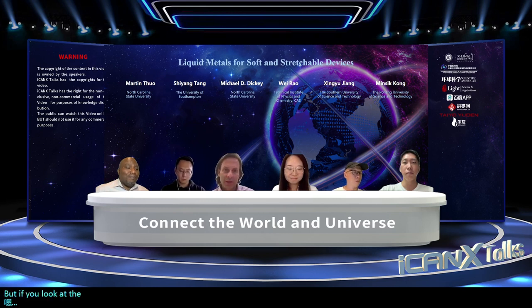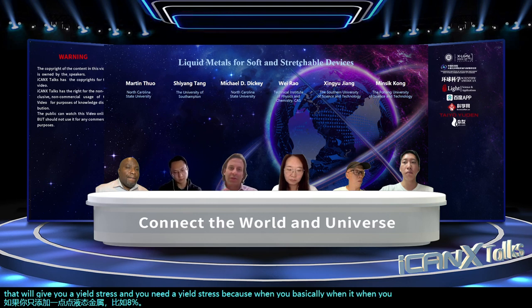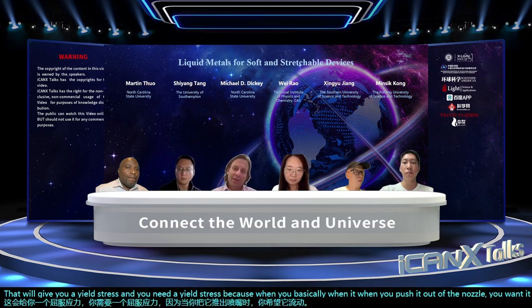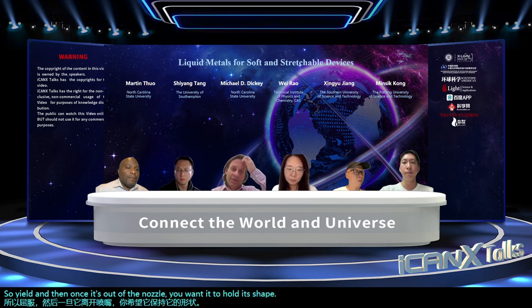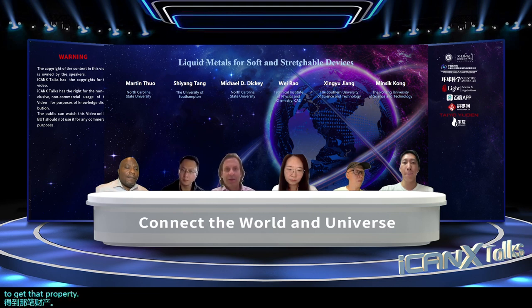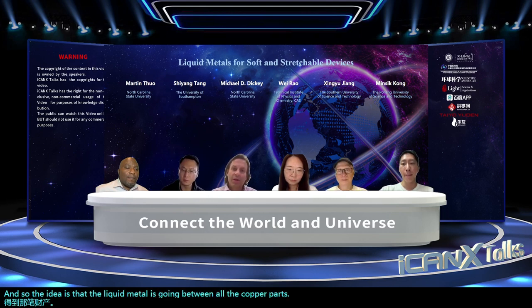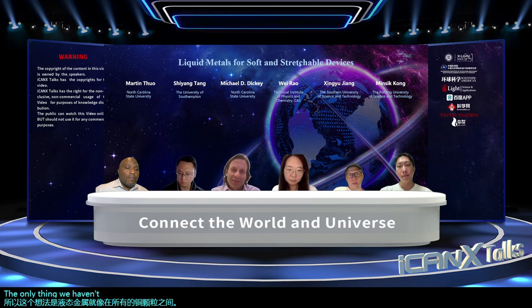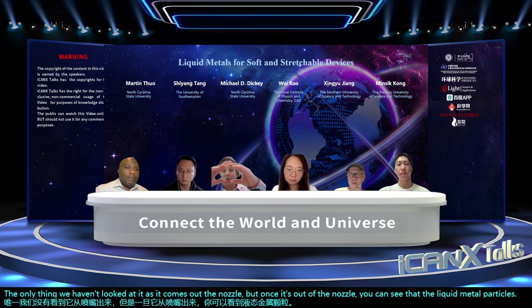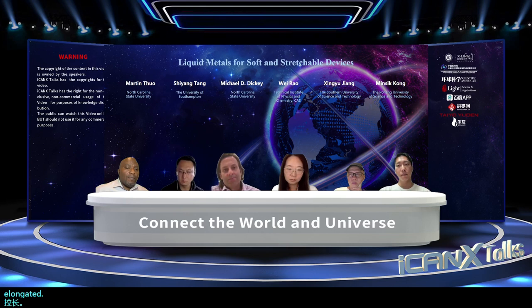But if you look at the rheology, what's interesting is that if you only add a little bit of liquid metal, like 8%, that will give you a yield stress. And you need a yield stress because when you push it out of the nozzle, you want it to flow, so yield. And then once it's out of the nozzle, you want it to hold its shape. And we only need to add 8% liquid metal to get that property. And so the idea is that the liquid metal is going between all the copper particles. We haven't looked at it as it comes out of the nozzle, but once it's out of the nozzle, you can see that the liquid metal particles go from being round to elongated. And so I do know that they're experiencing quite a bit of shear and that it will hold that shape.